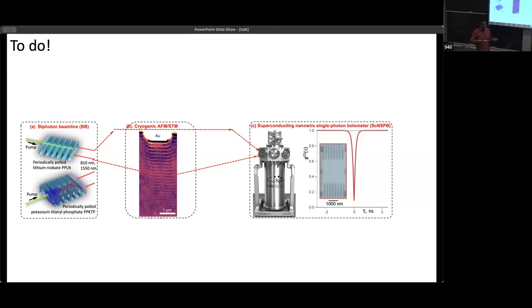The bubbles are weird places in these materials. Are there nonlinear processes that lead to heating? And if there are, does the heating not matter? Indeed there is heating. Whenever you turn the laser on, for example, the bubble might expand, and certainly your tip itself, which has a gold coating on it, absorbs some of that light, so it's going to heat up. As soon as you change the power of the laser, there are all kinds of drifts. So between each measurement, we wait and watch that drift die down over some period until it becomes stable, and after several hours, we take the next measurement. That's how we avoid that issue.